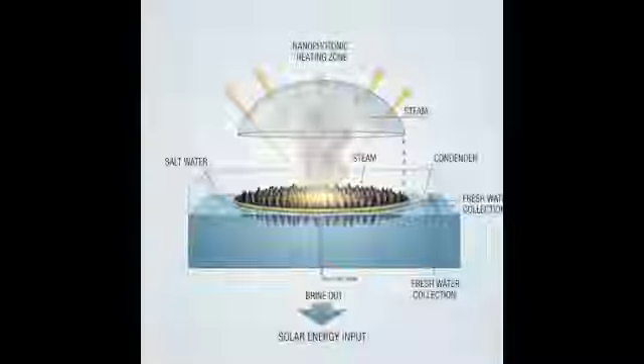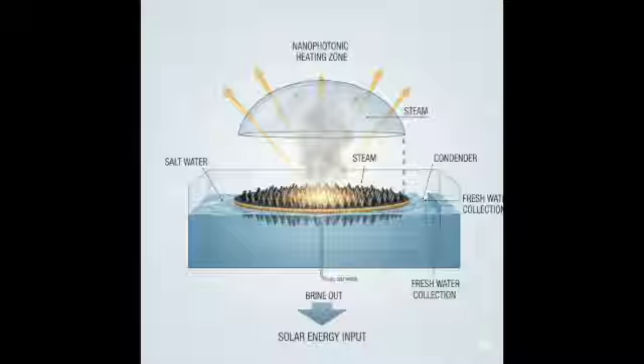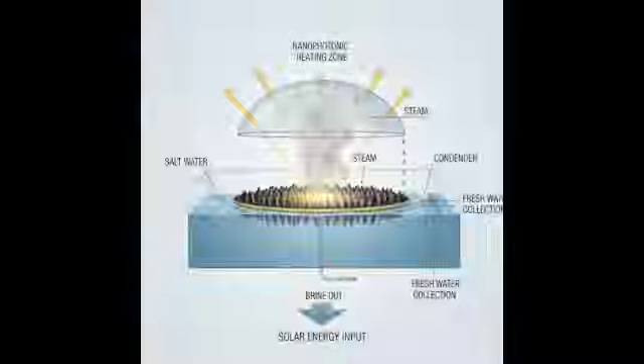The feed-facing side is designed to have some affinity for water and oils, amphiphilic, which makes it slippery to organic foulants. They don't adhere strongly. But the pore structure in the permeate-facing side remains strongly hydrophobic to ensure only vapor passes through and prevent liquid breakthrough. So it tackles fouling and wetting simultaneously, and dip coating enabled that. It's one feasible method. The study you cited showed stable operation for 10 hours using such a structure, which is promising for dealing with challenging feed waters.